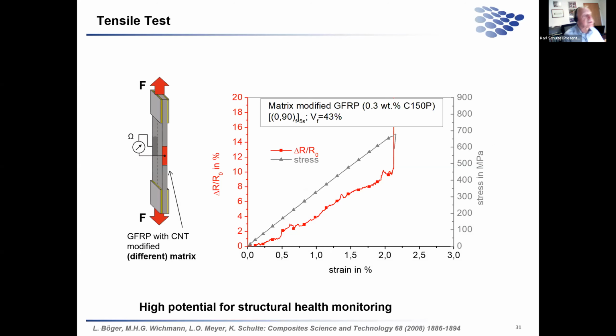Here it's shown on a test coupon. We have a test coupon with carbon nanotubes in the matrix, in this case with glass fibers, which are not conductive, but the matrix is electrically conductive due to the addition of carbon nanotubes. Then we strain and load this test coupon, it elongates as we can see, and this is a stress strain curve.